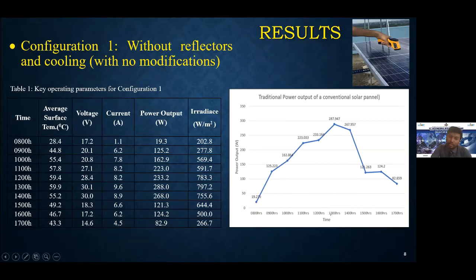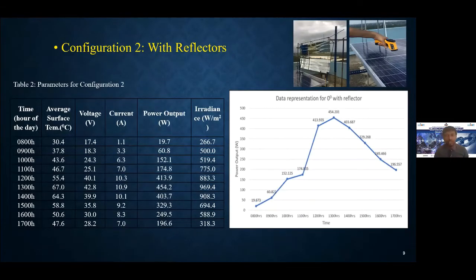From 800 hours to 12 noon, there's a gradual increase, and then at 1 o'clock, it reaches the maximum value. And then you have a drastic drop under configuration number 1. Now let's see what values we got under configuration number 2 with reflectors, and this is without cooling. So here from 800 hours to 12 noon, there's an increase, but the increase is not that much, right? And then it reaches a maximum value of 454 watts, and that is at 1 o'clock. Also you can see the maximum temperature of the panel reaches about 67 degrees Celsius. That is too high, because when the temperature reaches high, the efficiency of the panel moves down.